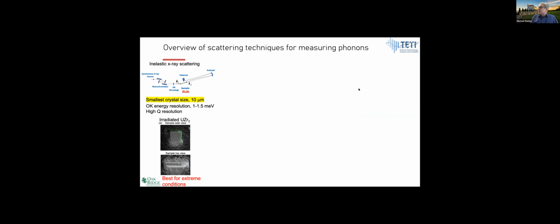I want to do a quick overview of different scattering techniques and their advantages and disadvantages. So for inelastic X-ray scattering, of course, you get the smallest crystal size possible. You get okay energy resolution. You typically get higher Q resolution, which can be very important if you have really steep dispersion curves when it comes to getting widths. And of course, because of the small samples and also the fact that you're not scattering from nuclei, it's good for extreme conditions like irradiated samples or also for pressure.